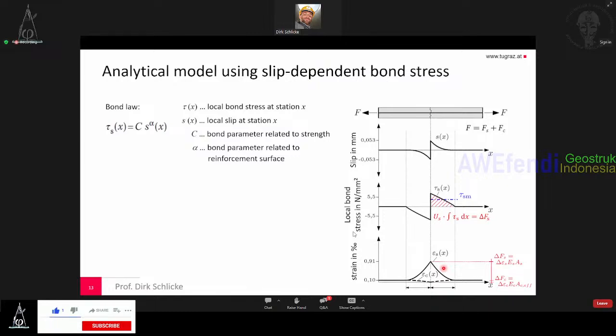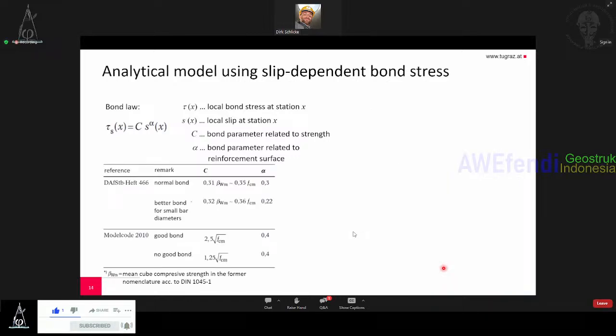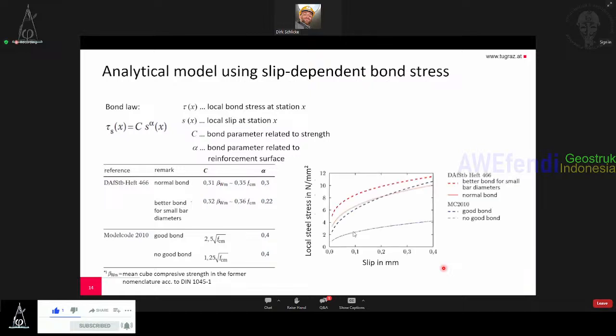There's also a force equilibrium in between, which means that the change of the steel force must be equal to the deformation of concrete for the same force. Of course, the bond law you saw here is then applied with some known parameters from the German code. And using this, you see the local steel stress over the slip performs like the red dashed line. This is what the bond law gives we use here.